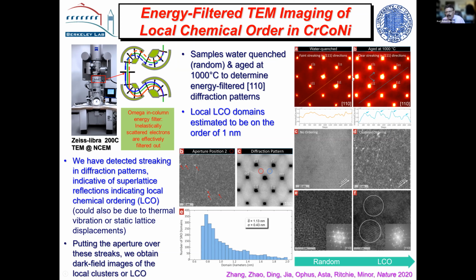But what we see are these streaking of these spots, which is evidence of superlattice reflections. You put the aperture on one of these streaks, take a dark field, and you can see these little clusters of atoms. You can see the formation of them in terms of the fast Fourier transforms here. If you map this out, we're seeing clusters of the order of about a nanometer, which are forming. And these are associated with what was originally seen by the XAFS and came out of our DFT, nearest neighbor interactions, the preference for unlike rather than like bonds. Now, that was, I think, the first direct evidence of local ordering in these materials.